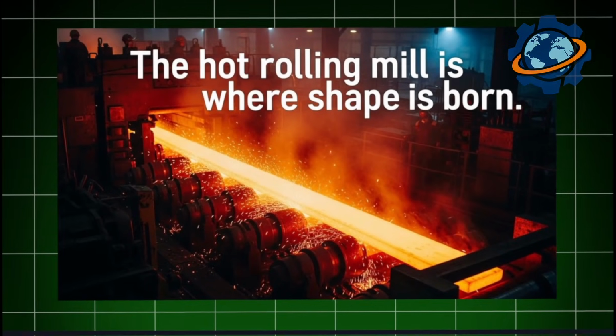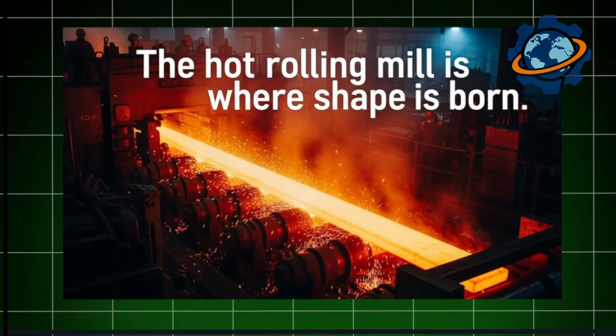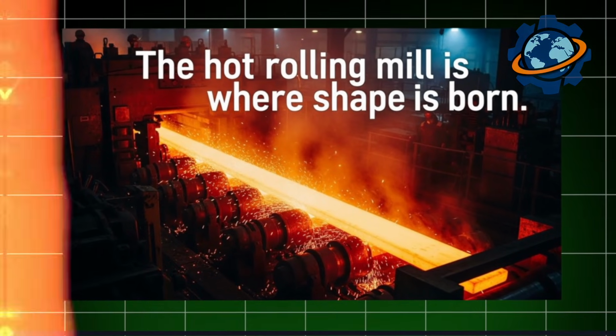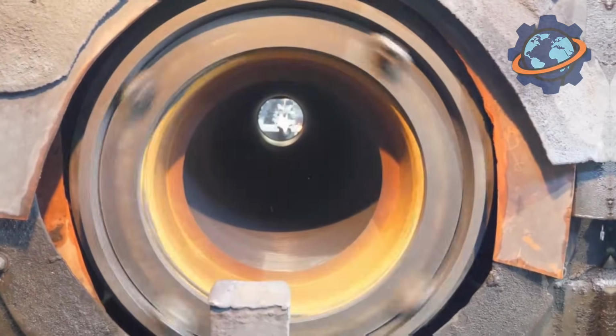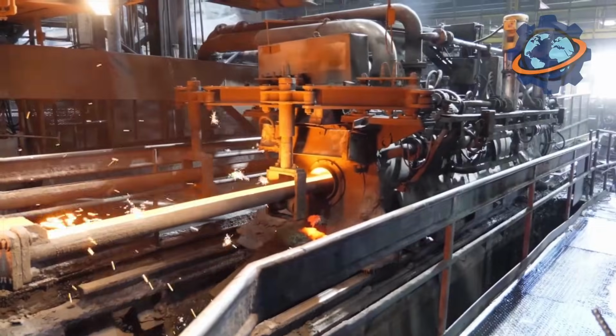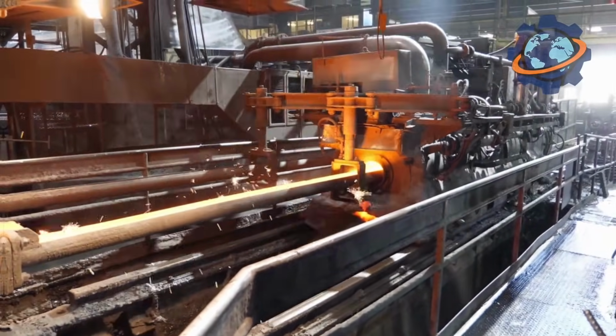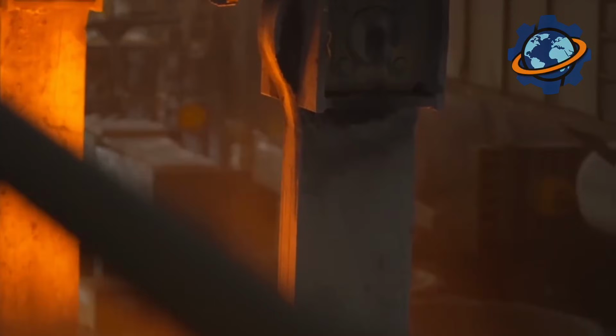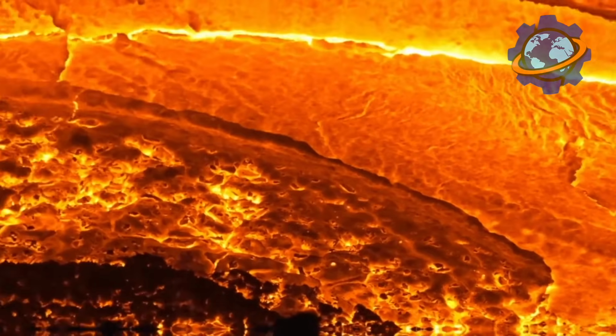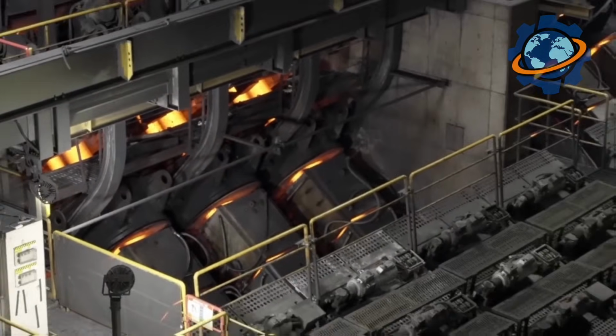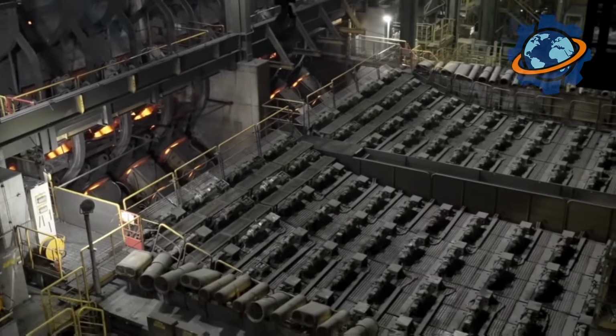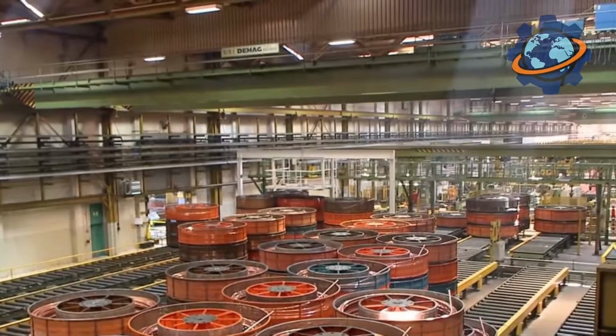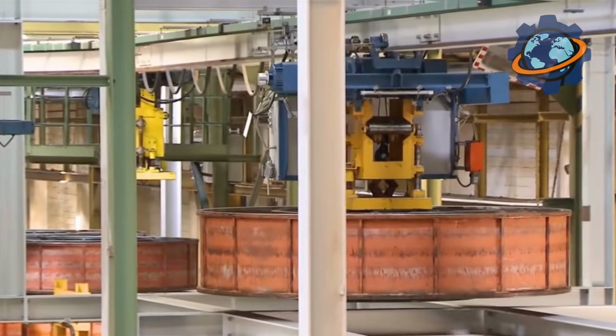The hot rolling mill is where shape is born. The continuous cast billet, still glowing red at 2000 degrees, enters the roughing mill. Giant rollers, each weighing 30 tons, squeeze the steel, reducing thickness while increasing length. The transformation is violent. 8-inch square becomes flat bar 6 feet wide and quarter-inch thick in 7 passes through successive roller stands. Watch the mill operation.